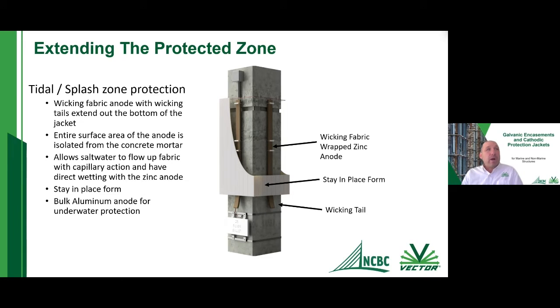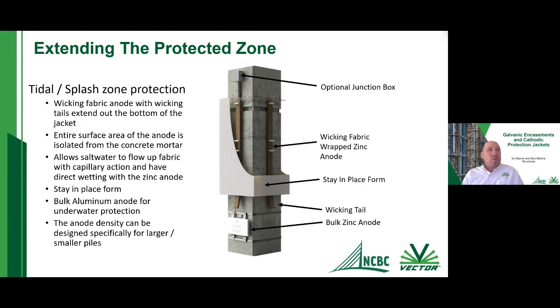And then as well, we're going to use a bulk aluminum anode for the underwater portions, for the submerged portions. So typically we were using a hull anode, but now we're also going to use a bulk aluminum anode that was designed specifically for cathodic protection on piles, and we're not just pulling an anode off of the shelf. And then one of the other things that you can have as well is an optional junction box.